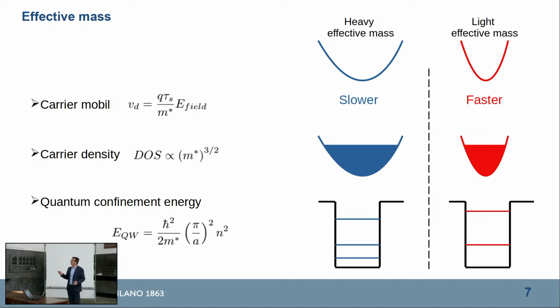Another class of phenomena where the effective mass enters is in determining the carrier density, or the so-called density of states. And here we have this dependence from the effective mass. So let's suppose that we have two bands with the Fermi level separating the occupied state and unoccupied state here. I mean, basically, the number of carriers I will have is proportional to the area of these two figures. So you can understand that with a heavier mass, I would get more carrier than with a lighter mass.